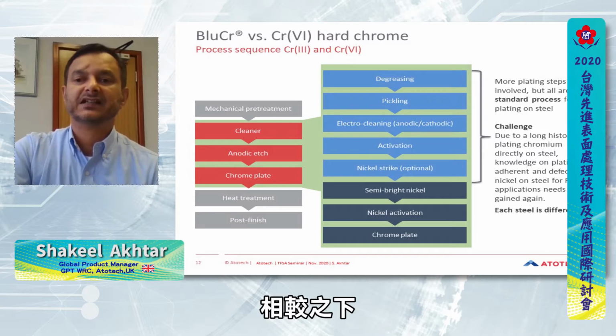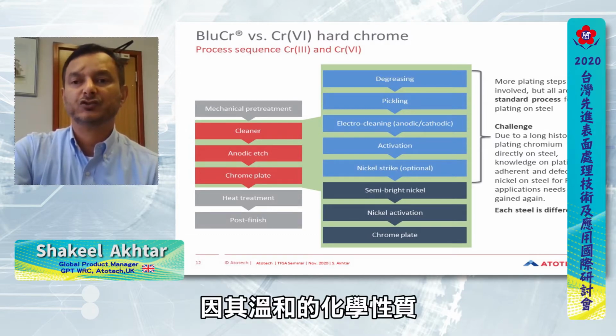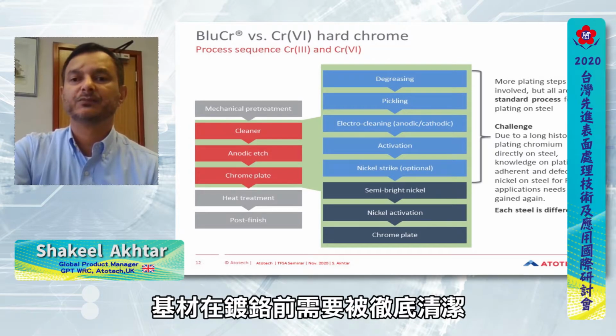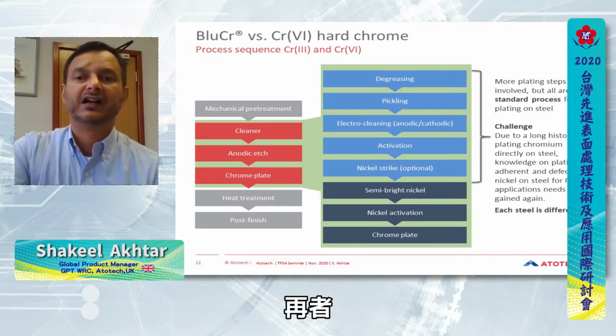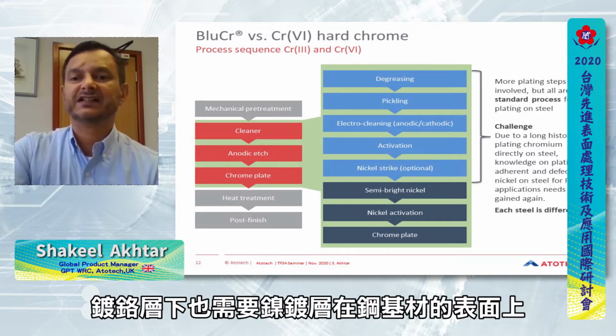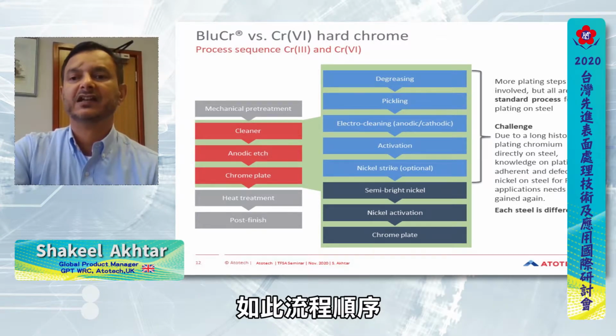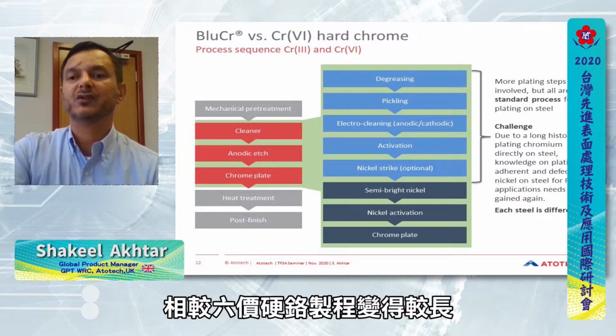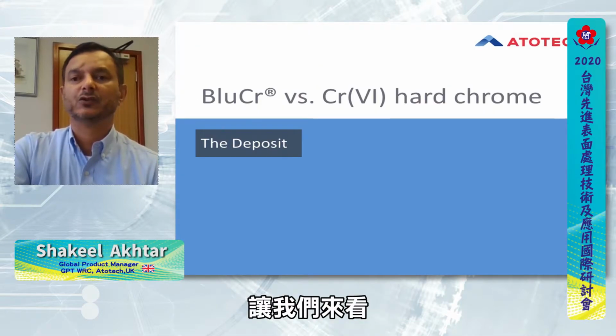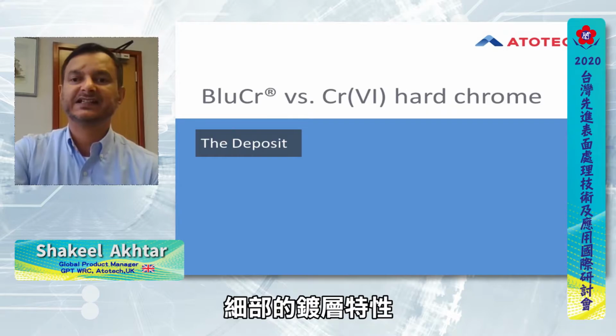In comparison, the blue chrome, due to its mild chemical nature, requires the substrate to be thoroughly cleaned prior to plating the chrome deposit. Additionally, it requires a nickel underlayer on the steel surface. Hence, the process sequence is longer compared to a standard hexavalent process. Let's take a look at the deposit properties in detail.